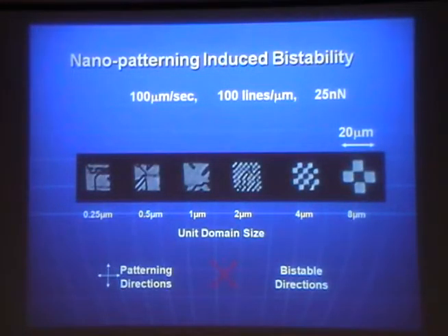So locally what's happening was exactly what I talked about. In each of the domains, the liquid crystal is undergoing a buckling transition. So these are cases where we make different size domains, starting with a fairly big 8 micron by 8 micron, and down to smaller sizes. After about 1 micron, we are no longer able to see the individual domains, but